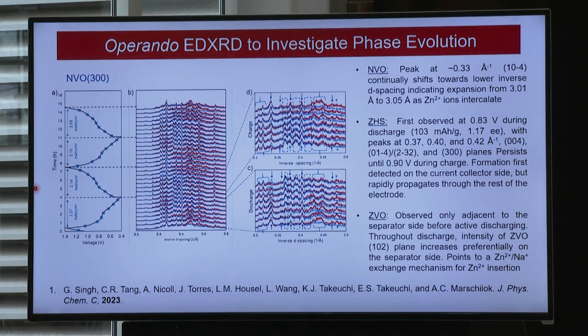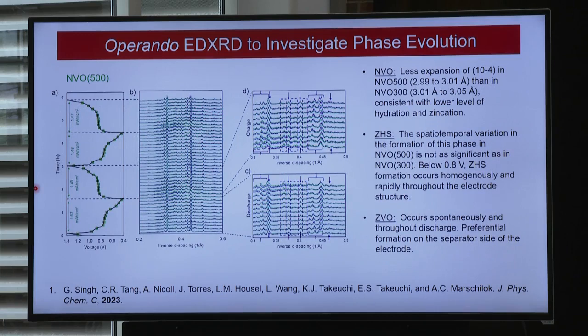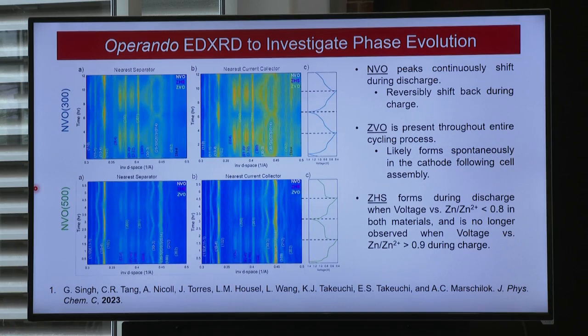And these are the X-ray results for the 300 degree material, and I won't go through the details here other than to show you we have the results on the 500 degree material as well, and I think it's more apparent here. As we charge and discharge, we can map where these various phases form and what's taking place inside the battery. And what we find is that for the 500 degree material, we're really only accessing the very surface layers of the material itself with limited amount of ZHS formation.